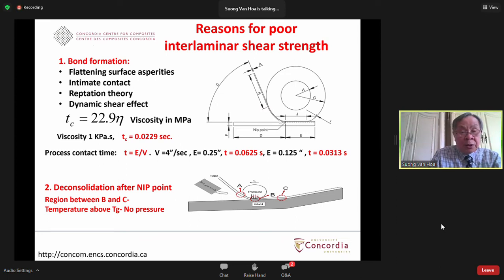Now, during this process, you can break it down into many steps. The first step is that the surface asperities have to be flattened. So between these two surfaces, there may be some kind of roughness, and this roughness has to be flattened, because it gets melted and flattened. Then the two surfaces have to get into intimate contact. They touch each other. Then the intimate contact has to be long enough so that the molecules of the thermoplastic can diffuse, can wrap across the interface to make the bond. Also, there is some kind of dynamic shear effect that may help to reduce the viscosity as well.